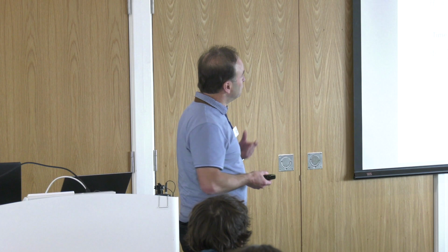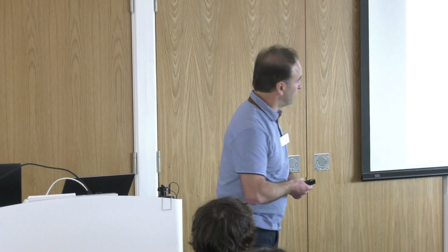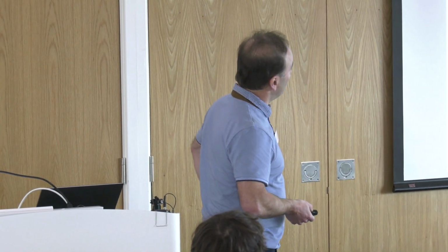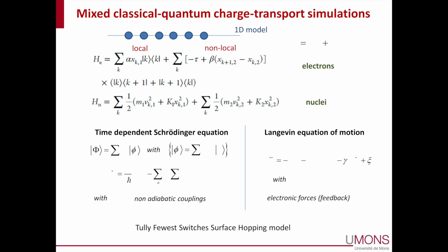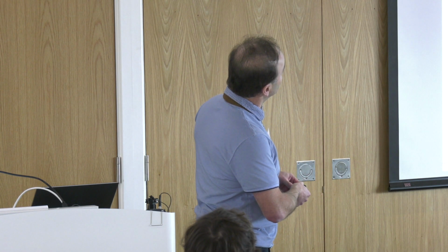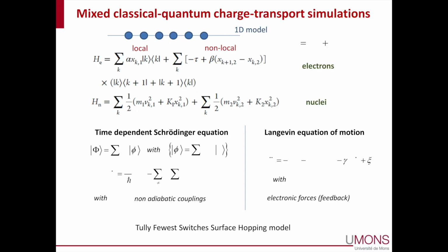Now, I would like to derive a model that is able to capture the two worlds, going from hopping to band-type transport. This is work that has been done by Lin-Jun Wang in our group 5 years ago, looking at model Hamiltonians. So this is a simple one-dimensional model, and we have coupling to a couple of vibrational modes that give rise to fluctuations in the site energy. That's called the local electron-phonon coupling, and in the transfer integral, that's called the non-local electron-phonon coupling.